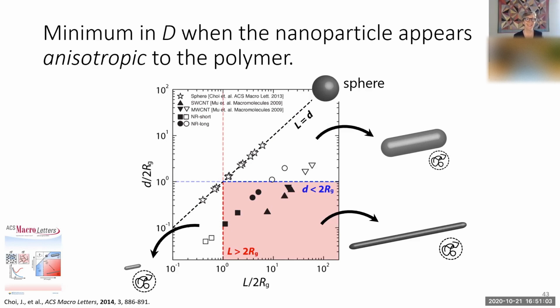I guess another quick question. When you have these really high aspect ratio nanorods, even if the center of mass has a relatively low diffusion, are the tips moving much more quickly than the center of mass? You mean like wobbling? Yeah. No. But actually you bring up a point. If they're really stiff, particularly the squares and circles, these are oxides, they're not bending, but they can move, they can jiggle. And the jiggle might allow for faster diffusion perpendicular to the rod than along the rod. Yeah, no, that goes the wrong direction. But we don't have a great mechanistic insight here.